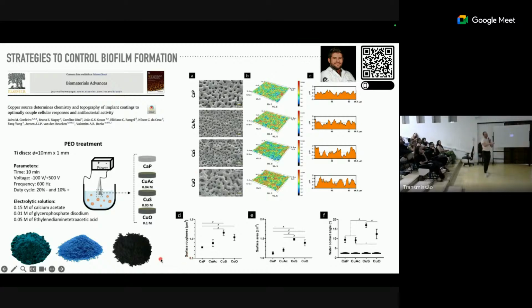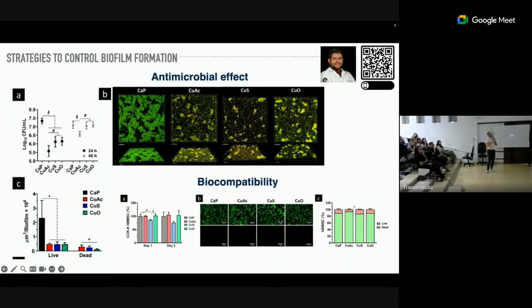We observe that the surface roughness of all these groups is in a good range, from 0.7 to 1.2 micrometer. The surface area tends to increase with the increase in surface roughness, and all surfaces were hydrophilic, as you can see, from 10 to 12 to 18 degrees with the water. But the interesting thing is the antimicrobial effect. At 24 hours of biofilm formation, we can see a good antimicrobial effect, like 2 logs of reduction. But when you go to a more mature biofilm, the antimicrobial effect was reduced quite a lot. So this is the problem of those surfaces.